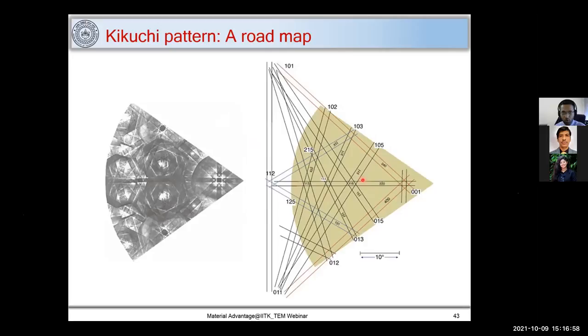So I talked about a zone axis. So let's say I have a zone axis 001 here, and I want to move to this zone axis. So how should I move? I should move along this Kikuchi line, or I should tilt my sample along this Kikuchi line so that I reach this 112 zone axis. So this helps us to tilt the sample.